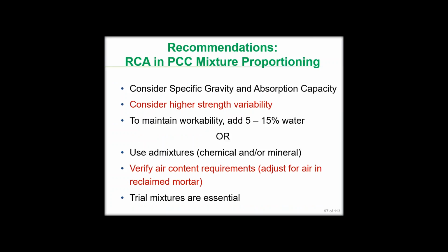General guidelines for using RCA in concrete mixtures, obviously consider the fact that you have a higher volume there, which means your specific gravity is lower. Your absorption capacity tends to be a little higher, so your water demands are going to be higher. There may be a more rapid loss of workability in the fresh concrete. There's often a bit higher variability in the strength.